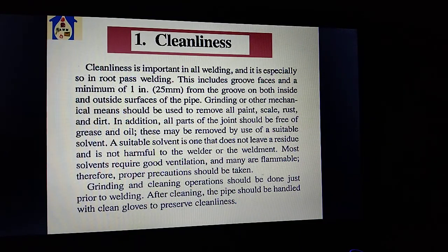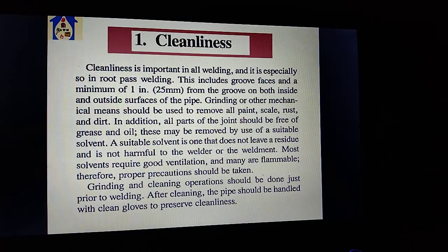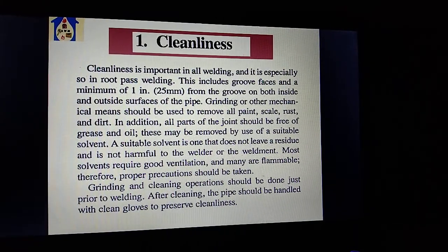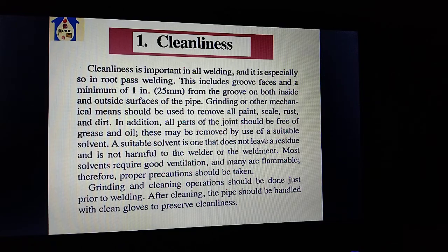Cleanness. Cleanness is important in all welding, and it is especially so in root pass welding. This includes the fusion face and groove face and a minimum of 1 inch from the groove on both sides and the outside surface of the pipe. Grinding or other mechanical means should be used to remove all paint, scale, rust and dirt. In addition, all parts of the joint should be free of grease and oil. This may be removed by use of a suitable solvent.